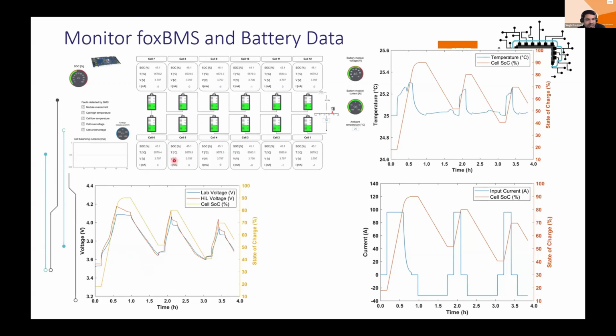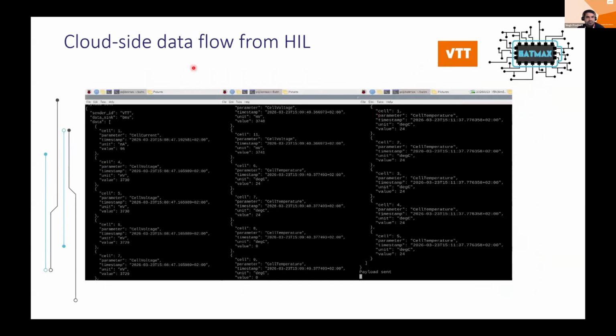Okay, so here it is showing the validation of our lab data and HIL data. And the most important thing was to monitor the temperature. So this is the cell temperature, and that is the set ambient temperature, and the cell temperature was varying very close to it during these operations. This indicates limited thermal stress during this applied maritime profile conditions, and also stable thermal behavior during the test duration.